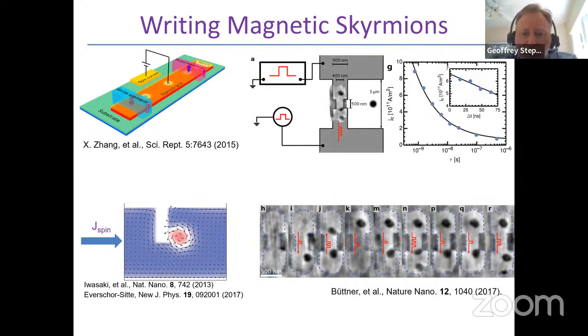And this has been shown experimentally, as I showed at the beginning of the talk. In this case, by using notches, current pulses can be used to nucleate in a controlled way a magnetic skyrmion in a track that can then be translated along the track. But current pulses cost energy. And energy, again, is what you want to minimize. That's one of the things that makes spintronic devices potentially of utility compared to conventional devices.